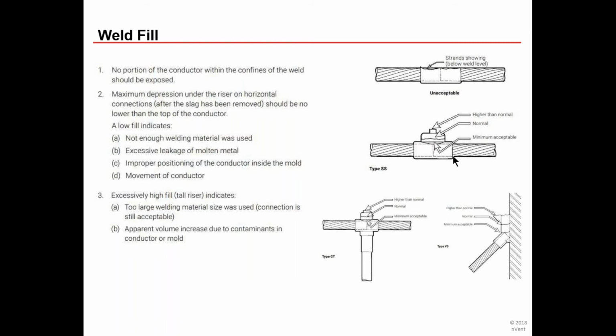You can also see here the minimum acceptable and the normal amount of weld for this type of weld. Minimum acceptable is that everything is covered. Normal is actually a little bit over that. Higher than normal probably means that you may have used the wrong weld material, or it's just slag that can simply be knocked off. So a couple things to look out for here. Again, no portion of the conductor within the confines of the weld should be exposed.